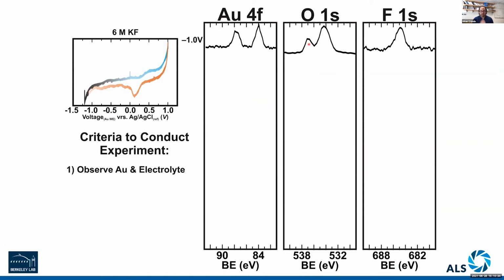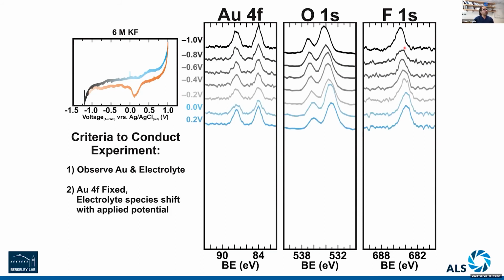So we've done the dip and pull. We're going to start at -1 volt. We're now probing through about a 30 nanometer thin film of water. We're seeing the solid of the gold electrode. We're seeing the vapor phase, the liquid of the electrolyte, and also the fluorine 1s from the electrolyte. When we continue to step up in potential, we're grounding our gold so it stays steady. Now we see again the electrical sensitivity. We're seeing a 1-to-1 shift of our electrolyte. That means we have a very electrochemically active location.